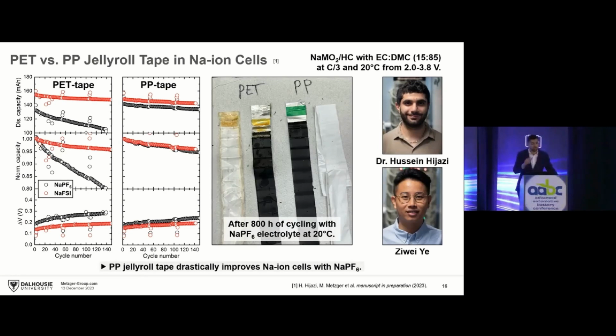In fact, this picture shows you what the tape looks like just after 800 hours of cycling at room temperature with sodium PF6. You see the PET tape, polyethylene terephthalate tape, is completely decomposed, whereas the polypropylene tape is stable.